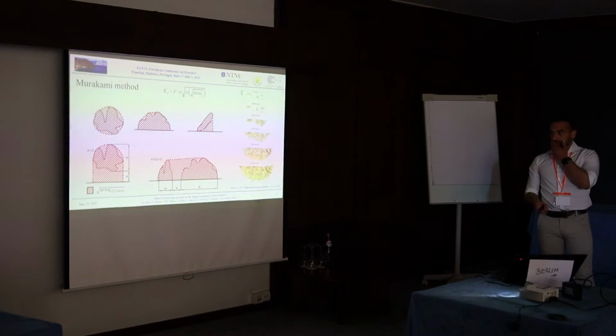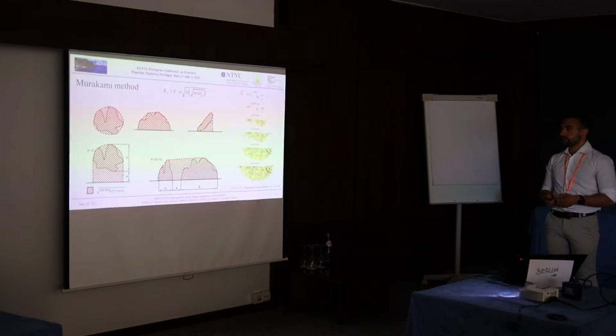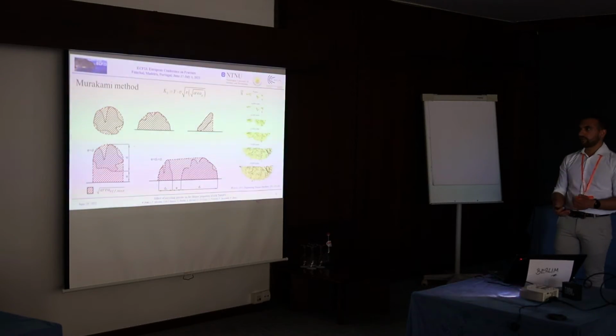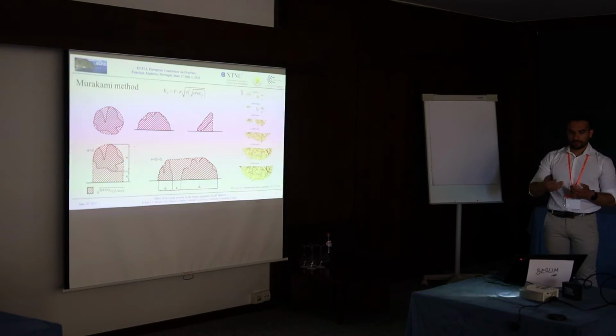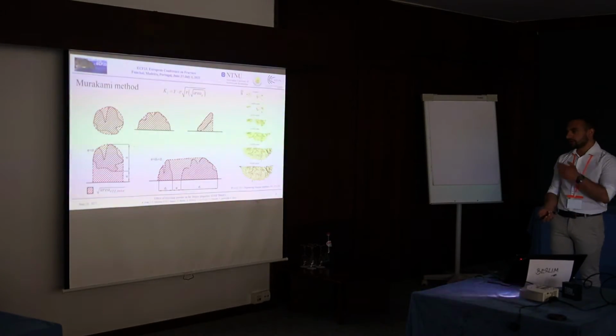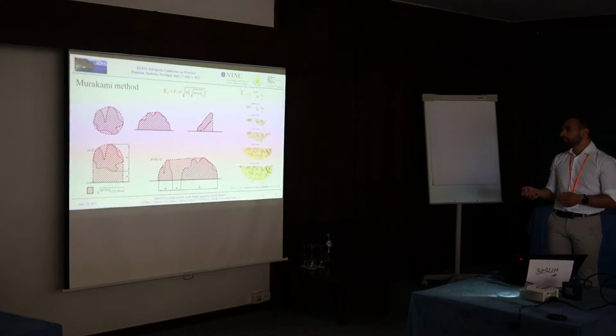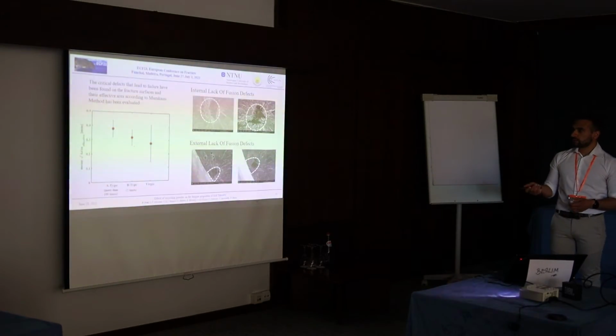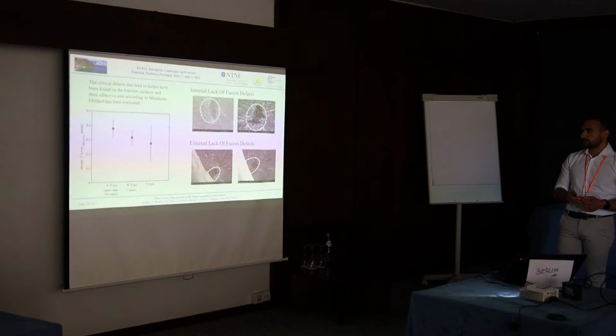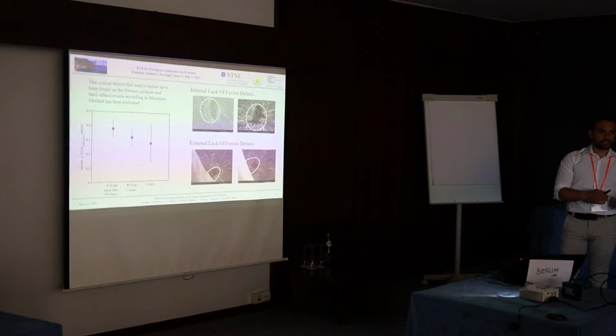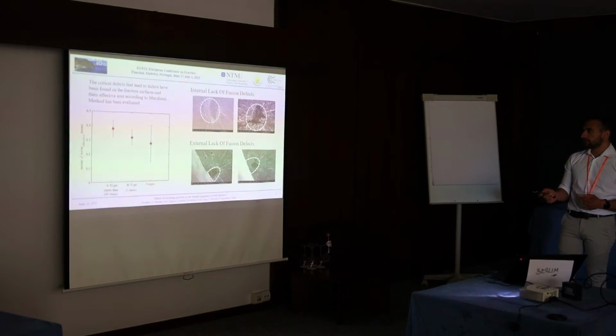We have considered the Murakami method in order to account for the defect effect, so that we can see the data without the effect of the defects and evaluate if the material itself was affected by the effect of the recycled powder. And we have measured all the values of the critical defects according to the Murakami method, evaluating the effective area for the defects, both for internal defects and external defects.